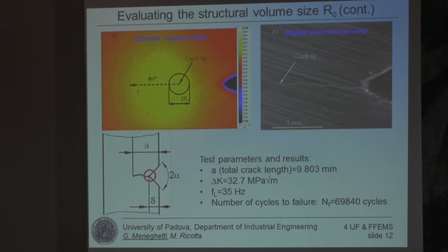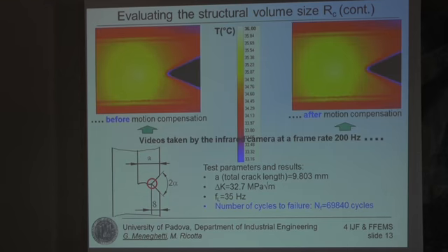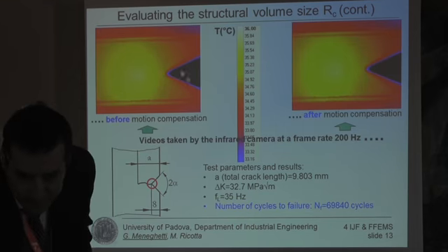In this specimen, we have a total crack length of about 9.8 millimeters. The range of the stress intensity factor at the crack tip in this experiment is 32.7 megapascal per square root meter, and the number of cycles to failure is 69,000 cycles. So let us keep in mind this number, 69,000 cycles.